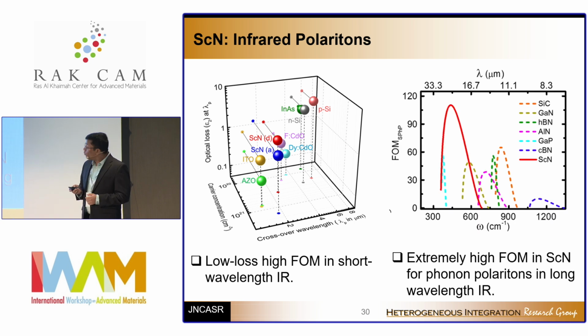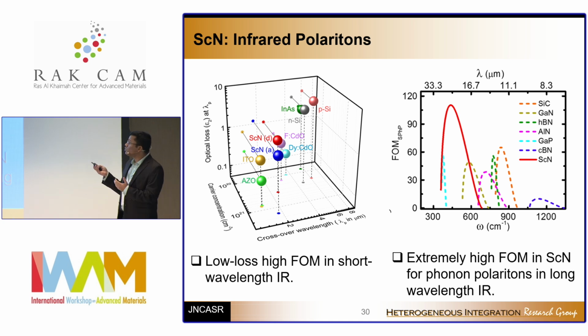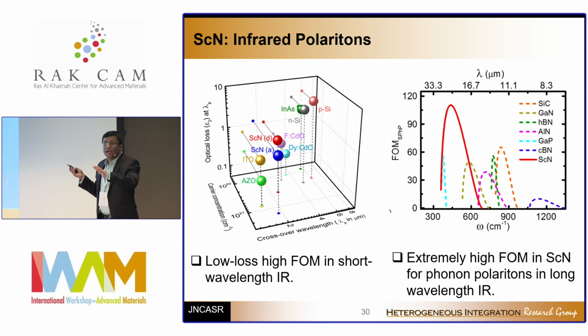In terms of phonon-polariton, the figure of merit, as we call it, and there's a mathematical expression to calculate it, I'm not showing it, but if you calculate the figure of merit, you see scandium nitride is much, much better than many of the other 3-5 semiconductors or polar dielectric media. The basic reason is that scandium nitride has a low band gap, so it has a higher epsilon infinity, and that basically leads to an extremely high figure of merit.